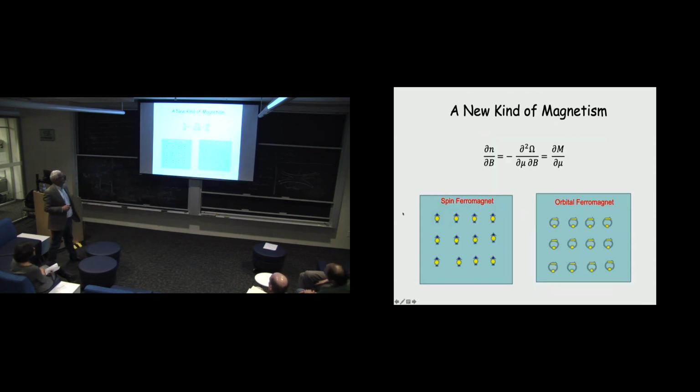And in fact, this is something we kind of understand. So this is what I showed you. The density at which the insulating state appears depends on magnetic field. And just from some Maxwell relations, this means that this sample has magnetization. We actually think it's purely orbital magnetization.